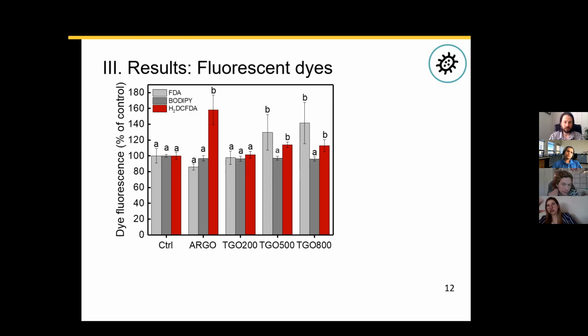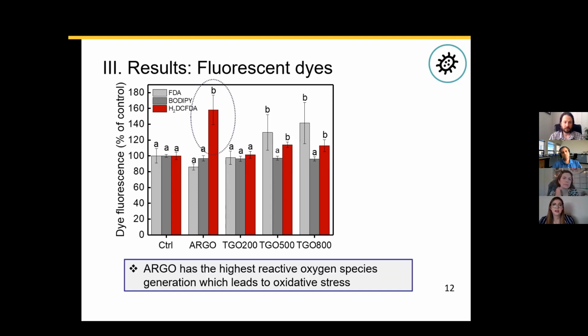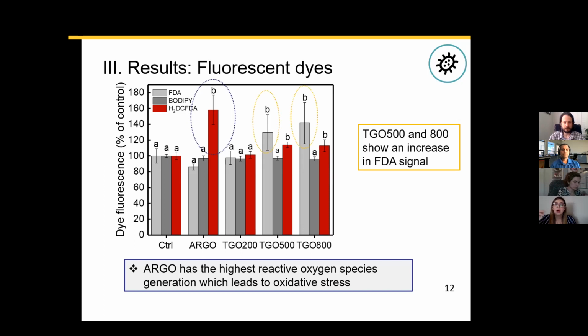Now, the first result that we see is that the as-received GO, which is the most oxidized material, has the highest reactive oxygen species generation, and this actually leads to oxidative stress. On the other hand, we see that the thermally annealed materials show an increase in FDA signal, and that is attributed to perhaps more interactions between the cell membrane and the materials, therefore leading to a wrapping mechanism from the material around the bacterial cell wall.